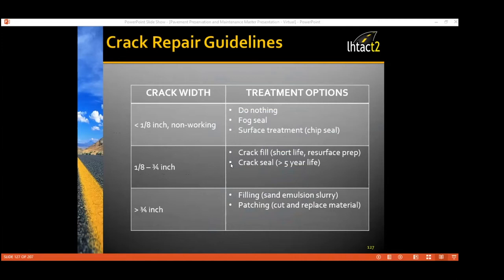So, crack repair guidelines. Just a general rule of thumb: if the crack is an eighth inch or less and it's non-working, here are some of the treatment options. We can do nothing, okay? Maybe that's not a real good option, but that is an option. We can put down some kind of a fog seal, or some type of surface treatment, a chip seal, because these cracks are very minor in width. And so sealing them with a sealant is probably not real feasible.